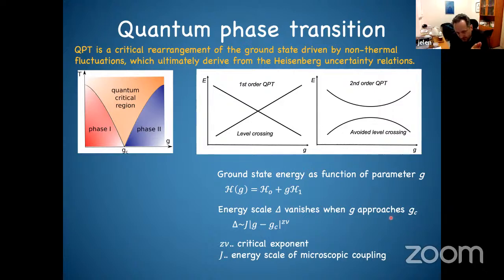But these days people also start to look at a different kind of transition which happens at zero temperature. There you can start to tune your system by different external stimuli. It could be pressure, it could be magnetic field, whatever, but not the temperature. And at zero temperature, at a certain critical point, you will go from one phase to another phase. So, for example, I can imagine that I have an antiferromagnetic solution, and at one moment when I start to apply the magnetic field, I will get a magnetic solution.